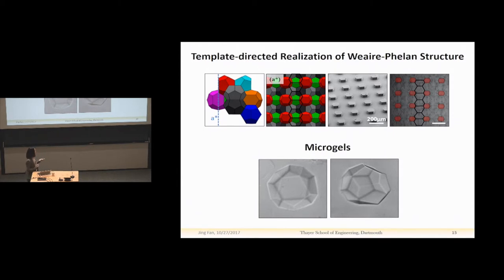And the reason why people didn't observe this structure before is because the Weaire-Phelan structure is not compatible with a smooth surface. Usually we use a container with a smooth surface to house the droplets. That's why people didn't observe it earlier. But once we give it a little guidance, they will be able to pack into this structure.